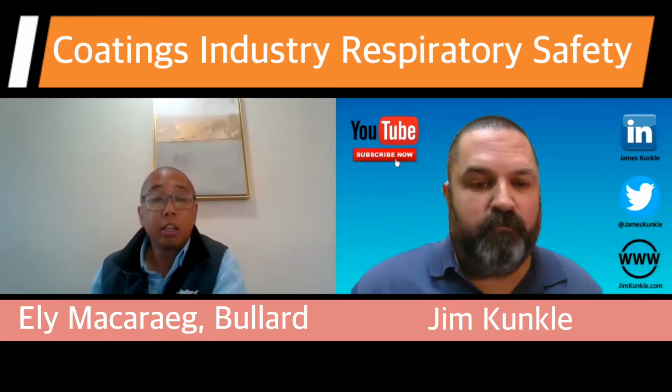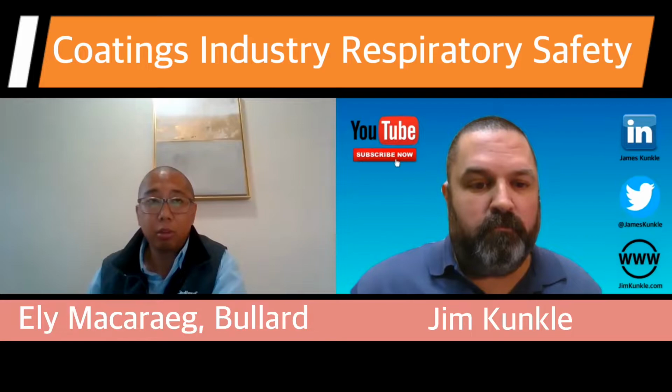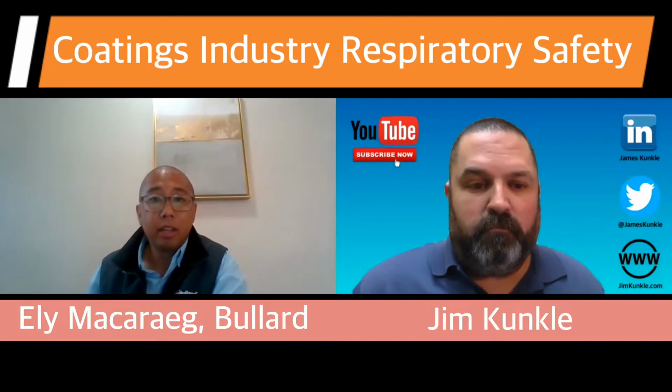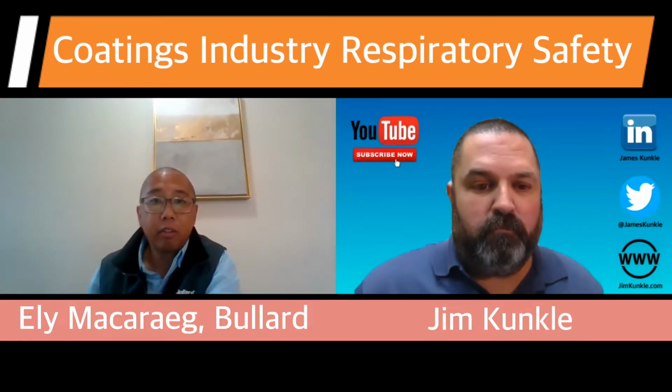Mm-hmm. But the primary contributor, and the largest contributor to contaminants in this industry, is the media that's being used. You have your coal, copper and nickel slags, glass, steel grit, garnet, and then silica sand, and hopefully a lot of that's already been wiped away. But these are what you would call the potential contributors, because when they turn into respirable quantities, things like aluminum, lead, iron, zinc can get in the air from these sources.